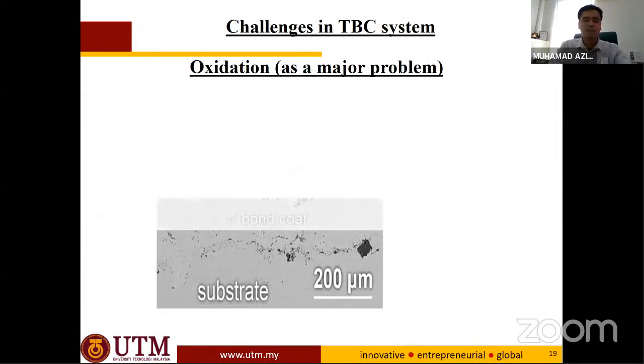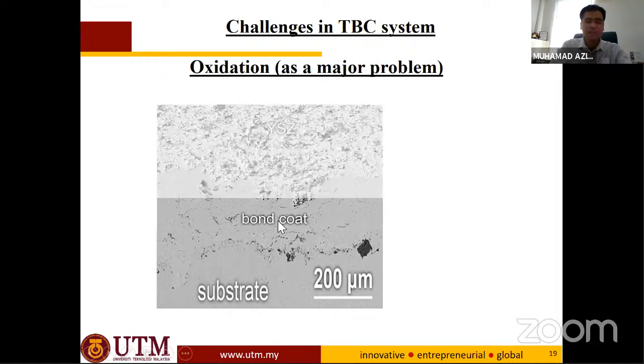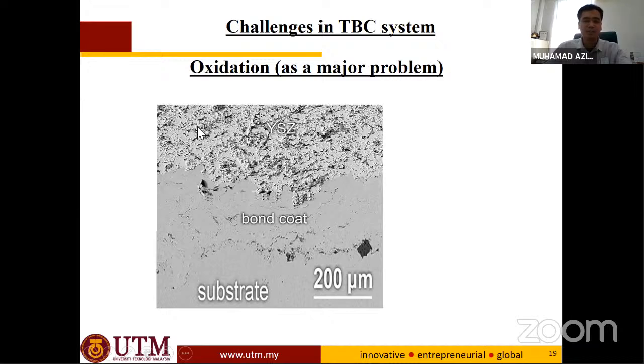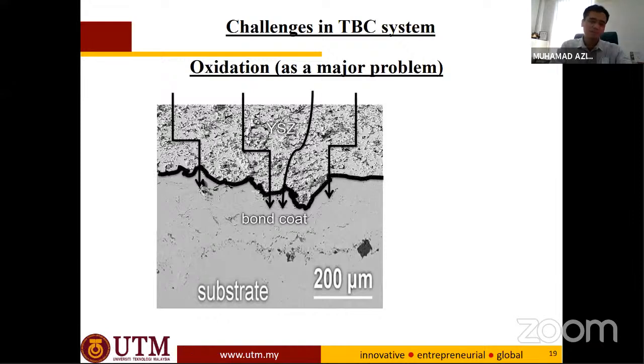Right, so oxidation, what's the problem? I mentioned just now, you have a problem with oxidation. You have the substrate, a nickel superalloy, for example, for a gas turbine engine. We have a bond coat made from nickel, chromium, aluminium, as just mentioned. And then we have another, which is the ceramic coating. You can see how the ceramic coating looks. It has a lot of porous structure there, okay? So this is basically the problem.